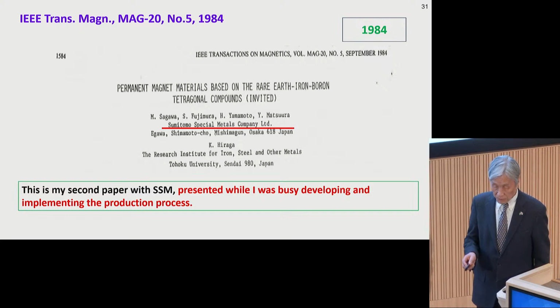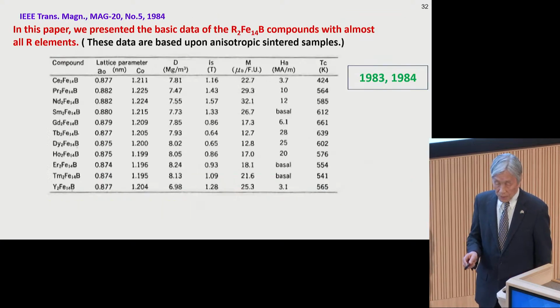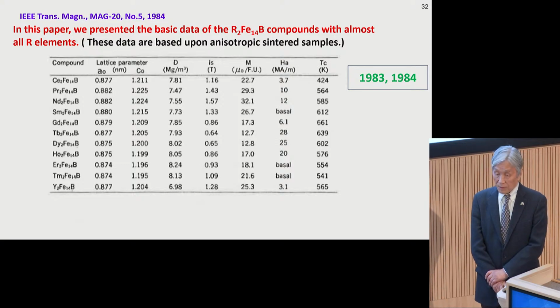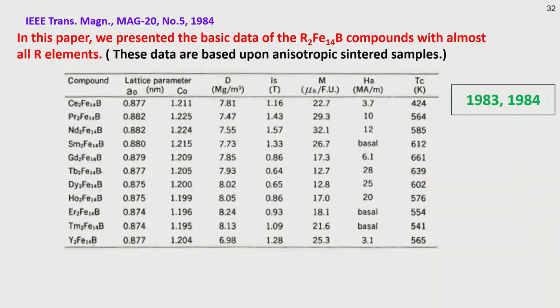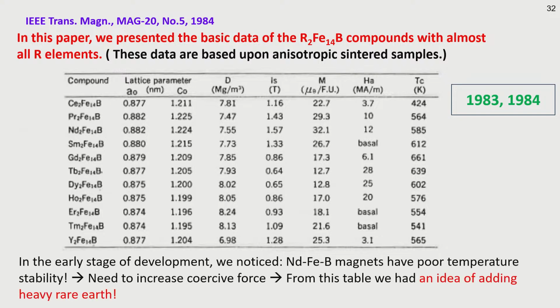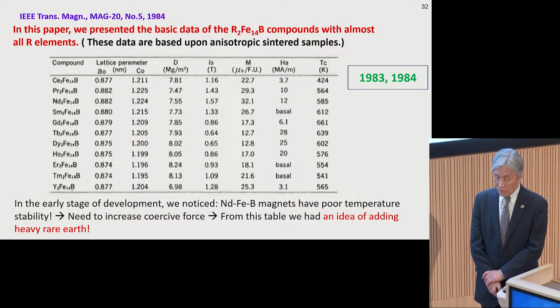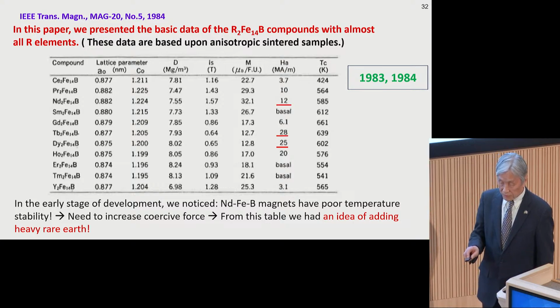Okay, this is the second paper from Sumitomo. And in this paper, we presented the basic data of the rare earth 2 iron 14 boron compounds with almost all rare earth elements. These data are based upon anisotropic sintered magnets. And in the early stage of development, we noticed neodymium iron boron magnets have poor temperature stability. So it's necessary to increase coercive force. From this data, we had an idea of adding heavy rare earths.